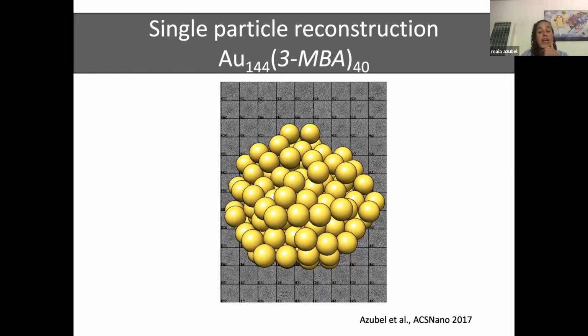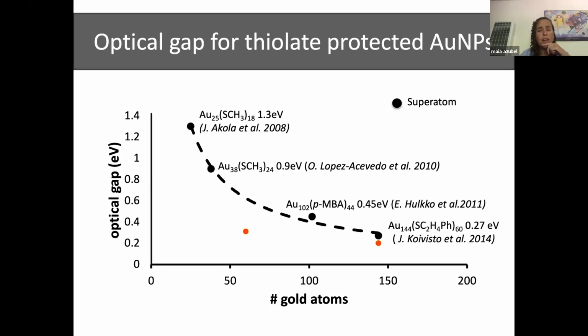And this is something that I didn't mention, and it's the fact that unlike crystallography, with EM, we can only see the core. We don't see the ligand, and that has to do with the fact that probably by the time we finish imaging, the ligands could be destroyed, but mainly because the ligand has atoms that are so much lighter than the gold that we don't get that signal.